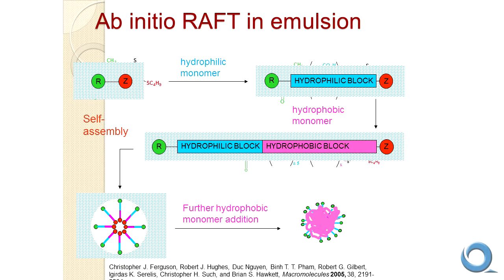So the way that we apply that to the synthesis of our nanoparticles, we start with a chain transfer agent with the leaving group and the stabilizing group. We have a hydrophilic monomer. We do the synthesis in aqueous solution. And we initiate and allow a hydrophilic block to grow under controlled conditions. And so as an example, this is the chain transfer agent that we're using. It has an ionic leaving group and a hydrophobic stabilizing group.